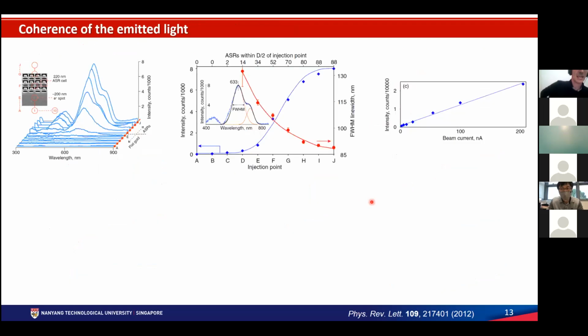In order to test this experimentally, we created an array about 30 by 30 microns with a unit cell of 220 nanometers, where we have this asymmetric split ring. Then we illuminate with the electron beam, and we approach the center of the array step by step. You can see here from the picture that the emission changes the more we approach. When we analyze, we see that as we bring the injection point closer and closer to the metamaterial, when we start engaging more than about 5 units, you start seeing emission. The emission picks up until it saturates, and at the same time, you see a linewidth narrowing, which is a sign of a temporal coherence being built.